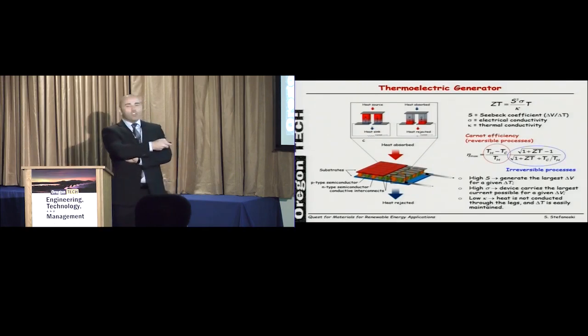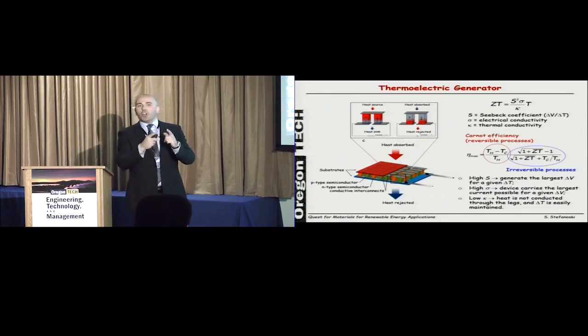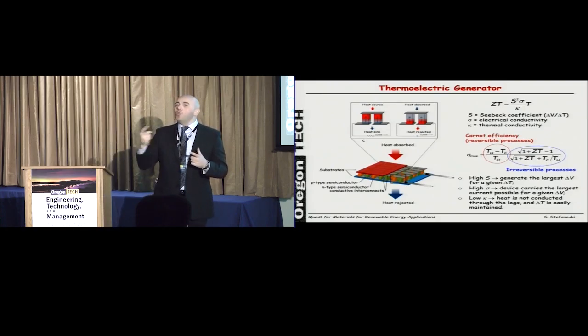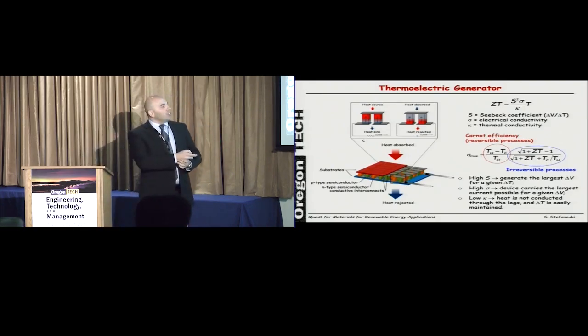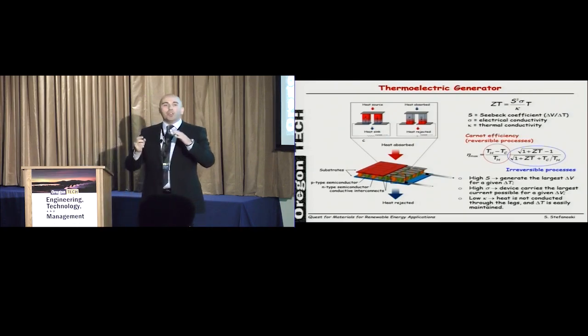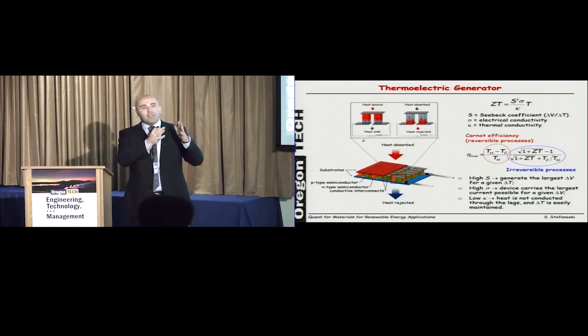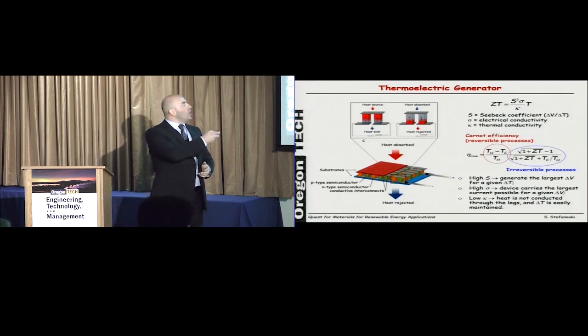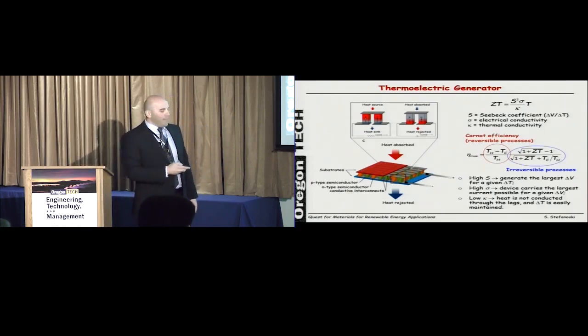need a high Seebeck coefficient, which means we need large voltage generated per unit of temperature difference. We need good electrical conductivity. These charge carriers have to be able to move freely in our semiconductors, and we need low thermal conductivity, which means we need to maintain the thermal gradient. We don't want the heat to be dissipated or the charge carriers just to travel to the other end and the effect to be terminated.